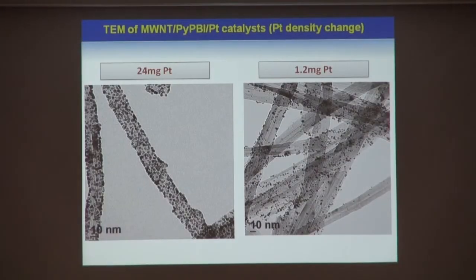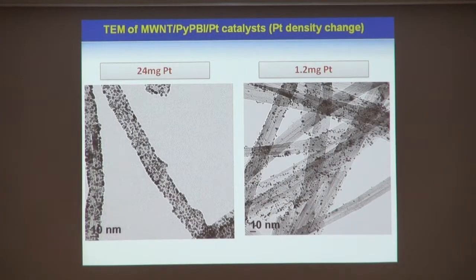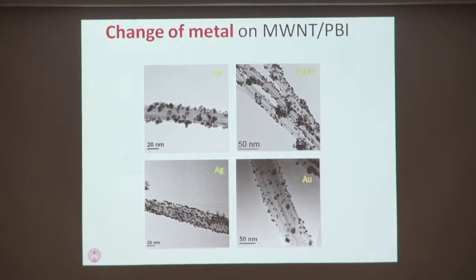So we have some results. So this is a present result. So you can see many platinum onto the surface of the carbon nanotube, but we can reduce the amount of platinum onto the surface, so density is pretty much different. So now we just started to examine the performance of this catalyst. And core shell structure is important. Also, we can change metal from platinum to palladium, Ag and Au like this.